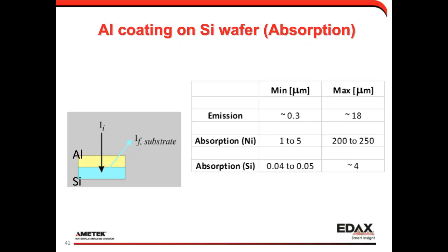So now we summarize all the various measurements that we've made here. We've looked directly at the emission signal. The emission signal shouldn't really vary between whether you measure it on nickel or on silicon. There'll be some variation in terms of the minimum limit, but the maximum is going to be dictated by the energy of the aluminum, so that's not really going to change based on the substrate. You can see in the absorption measurements the differences between the minimum measurement range based on whether you're measuring on a high energy signal like nickel or on a low energy substrate like silicon. And you can see the impact it also has on the maximum levels. There's quite a bit of difference in the range of what we can measure depending on the setup that we're trying to measure.